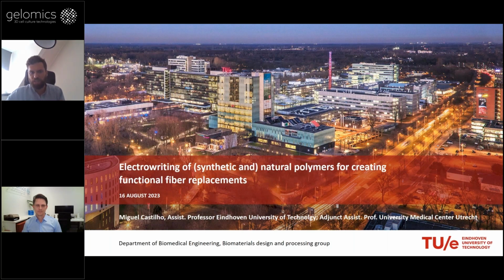So there is some work needed here to see how we can bring low, and here I'm saying from the top of my mind, the 15 microns distance of pore size. It's one of the limits, but it requires more work to understand how we can go low. But I would say if you want to control the pore size, until 100 microns it is basically just designing your construct that dictates the pore size.